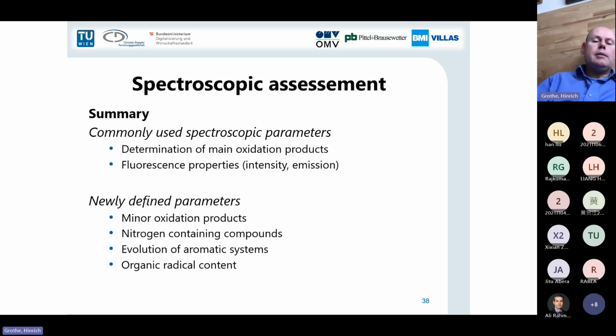To sum that up a little bit, we are doing a spectroscopic assessment, and we are looking for the determination of the main oxidation products. We are looking for fluorescence properties, intensity, and emission, and we can try to define parameters like the minor oxidation products, the nitrogen-containing products, the evolution of the aromatic system, and the organic radical content. Here I have shown you with the EPR spectroscopy.